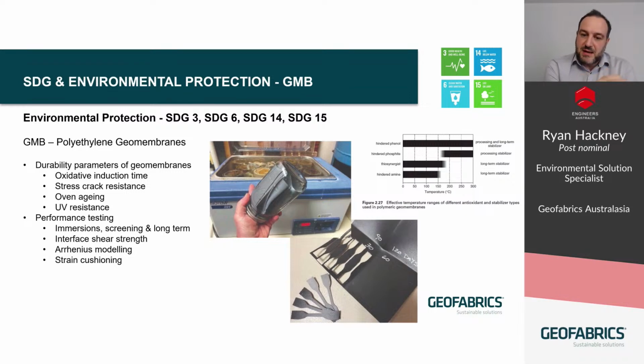So it's really important to understand the effectiveness of those additive packages, and we can measure that by a property such as the oxidative induction time. So we can immerse the material in these liquids of concern, and then at various time periods of immersion, we can take a sample and measure what the oxidative induction time is, and that will tell us how effective that package is over time.